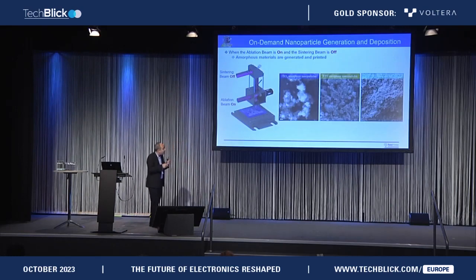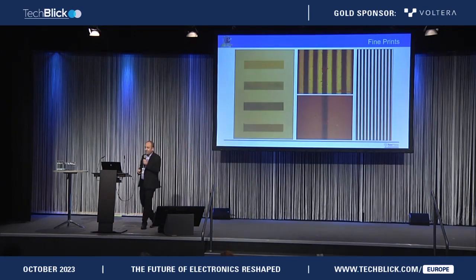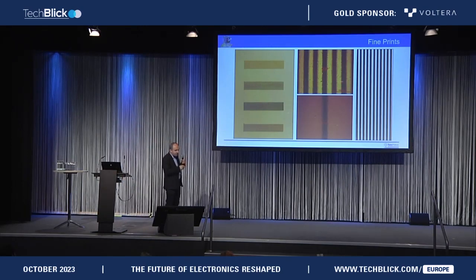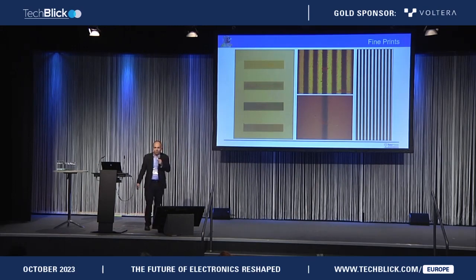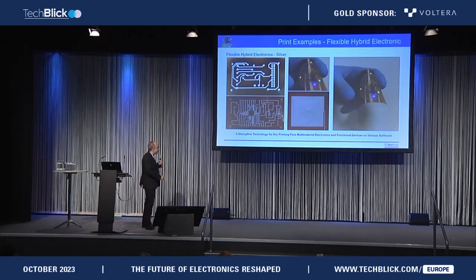Now, if you create a jet out of those nanoparticles, you can deposit these nanoparticles on your surface. And if you have your printing system with CNC integrated, then you can print beautiful lines with high uniformity, with high purity, just like this. Just before I came here, I printed these. This is about 50 micron through a 50 micron nozzle. All right? And of course, this one is unsintered, and if you sinter it, then it becomes a beautiful sintered line.